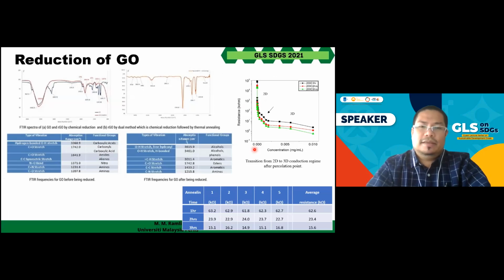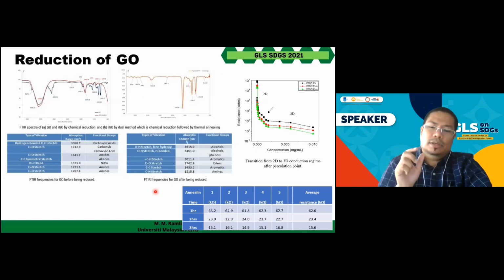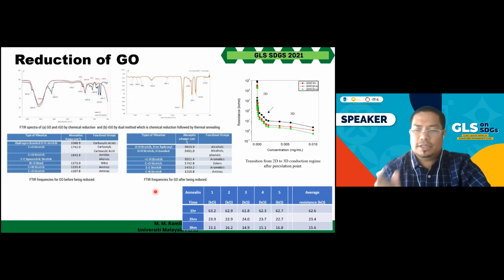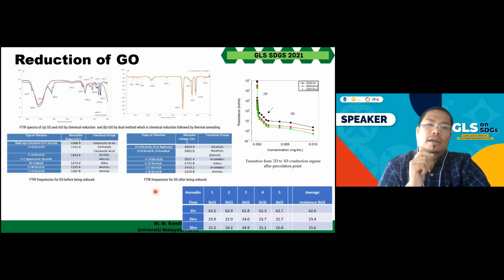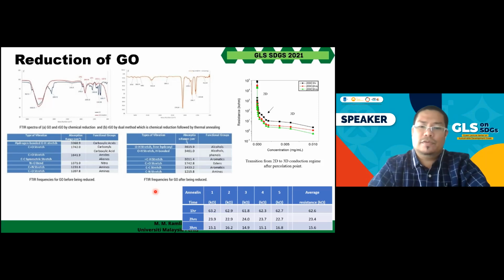So once we get the graphene oxide, we have to reduce it, we have to get rid of the functional groups on the graphene basal plane, because most of our applications are electronic applications. So we have to tailor-make our graphene oxide into the electrical connectivity that we want for that particular application. For example, we have two types of application. The first one is the gas sensor. For the gas sensor, definitely we need our reduced graphene oxide to be in the kilo ohm range. Okay, but for our second application, which is the biosensor, we don't have to make our reduced graphene oxide in the range of kilo ohm.